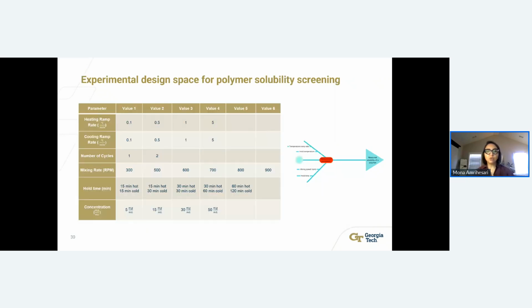So this slide shows the experimental design space that we were looking at. We have heating ramp rates and cooling ramp rates. We keep both of them the same because changing one versus the other might change the solubility behavior of the polymer and the metastable zone widths that we were looking at.